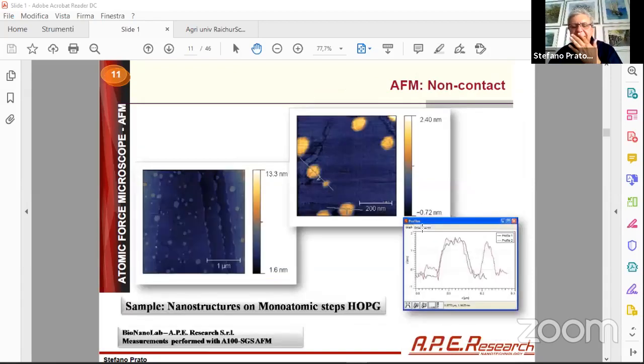Okay, this is an example. This is one of the few examples that I have about agriculture application. This is a nano fertilizer, some molecule that contains iron, made in a small nanoparticle. The aim of this group was to study what is the medium size of this nanofertilizer. What we did with AFM, this was in solution, so we put a drop of this solution over a sample that in this case was again highly oriented pyrolytic graphite. It's a piece of graphite that is very flat, atomically flat, I would say. Then we let the solvent evaporate, and we saw the particles that were left behind on top of the surface.